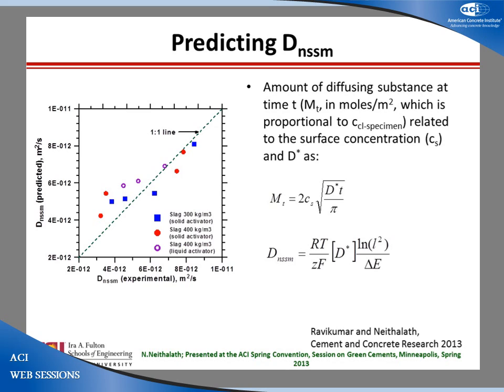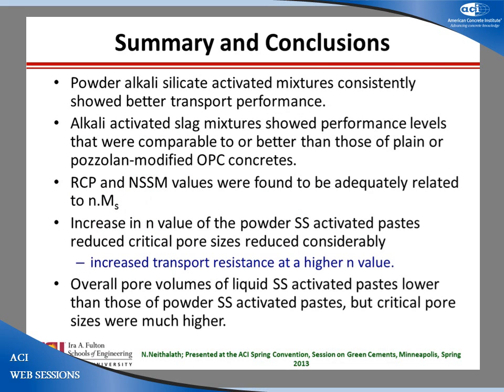Basically what you do is measure the charge, and if you can get a correlation in the lab, I can do only a half an hour RCPT, or whatever half an hour charge measurement, compare it, have a calibration chart, get that, extend it without doing a test, and you can actually predict the migration coefficient. It makes for a very easy, quick test, and then you can use this back to predict, based on what migration coefficient you want, what activator content and activator concentration you need to get a certain transport property, a certain strength. So it gets you a big picture of combining both mechanical properties and durability with mixture proportioning. We still have to draw some more lines in between the triangles, but the three corner points are there, which we can use as a base.